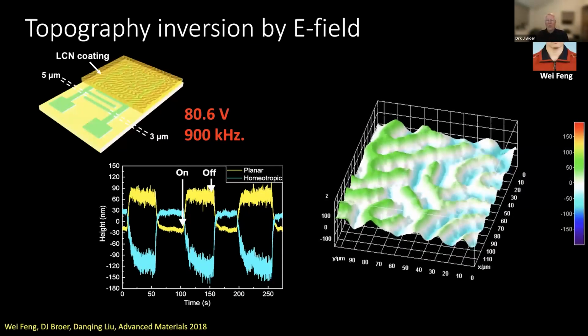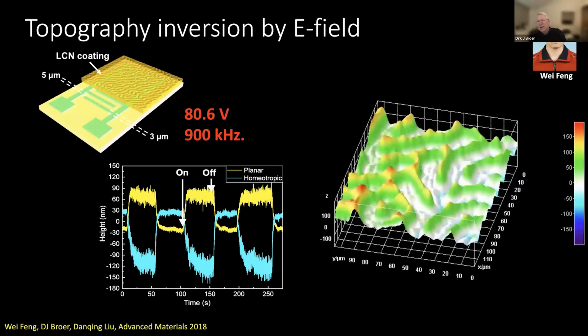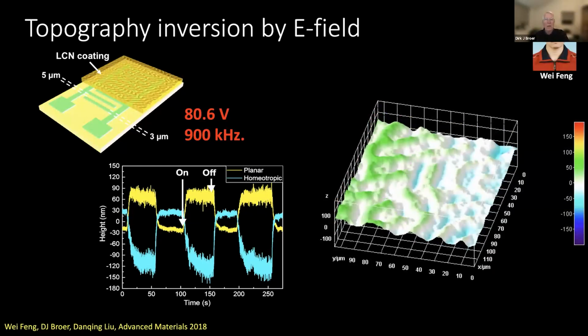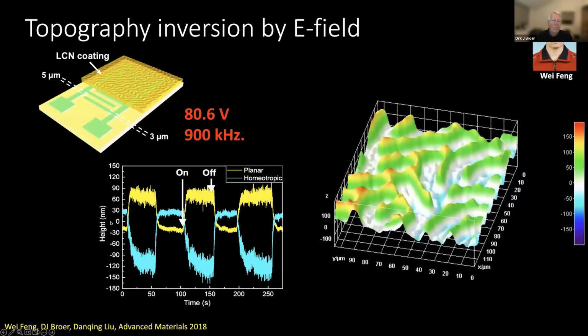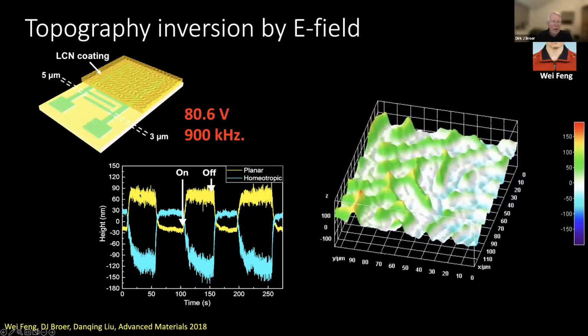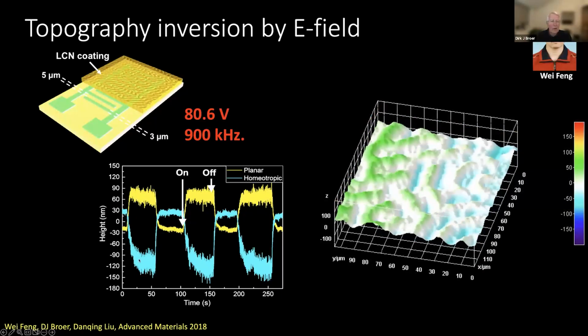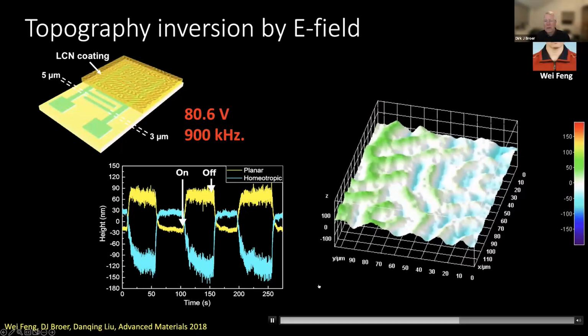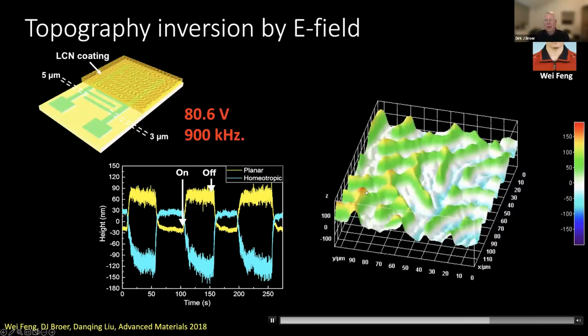Now, this was by light. We can also do similar tricks with electrical fields. Of course, then we need to add not the UV absorbing molecules, but molecules that respond strongly to the electrical field. Also in that case, we play with the other parameter in the system, and we can convert the fingerprints. The locations which are high initially become low, and the locations which are low become high again. So again, we can convert the system in a similar way as we do with light, as also shown in this movie.